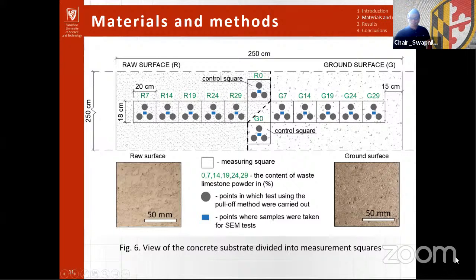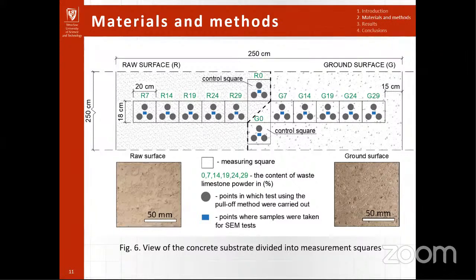Before applying the coating, we examined the morphology of the concrete surface using a 3D laser scanner under each measuring point where pull-off tests will be carried out. Then we made the coating. We covered control squares with epoxy resin without the addition of powder, and the remaining squares with epoxy resin with a gradually increasing content of the waste limestone powder. We added the waste limestone powder to the base layer in an amount from 7 to 29%.